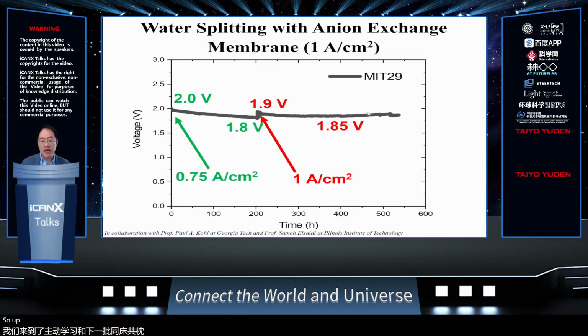So with that, and in collaboration with Professor Sameh Elsaidi and also Professor Paul Kohl at Georgia Tech, we're able to make an alkaline water splitting device with the anion exchange membrane electrolyzer at room temperature with very high current density. So this is close to the industrial requirement. 1 ampere per centimeter squared is very, very good at room temperature.